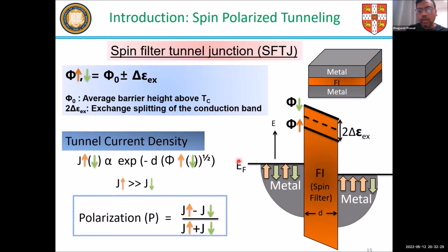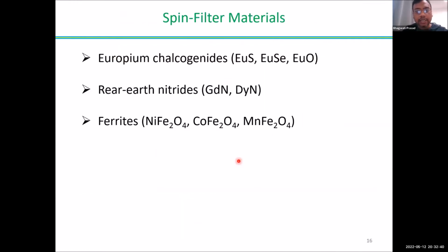Okay, so what you need for this kind of device is a material which is ferromagnetic as well as insulating. It seems a little weird, a rare combination that you see in nature, but there are some. The europium chalcogenide system, which Professor Jagadish Moodera from MIT has investigated a lot, performs really well, but you need certain care to grow these material systems. It's not straightforward, and also the Curie temperature of these material systems is lower.